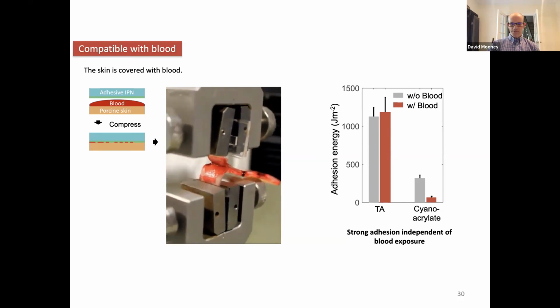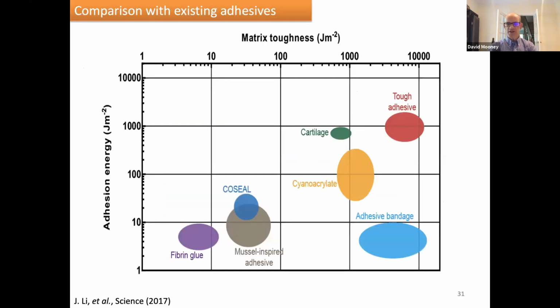still allowing us to use it in these kinds of bloody environments. Now, to put this in context from other materials that are out there, the tough adhesive in terms of both its matrix toughness and its adhesion energy functions in this regime. The cyanoacrylates that many of you are familiar with are over here. The PEG-based materials such as Co-Seal and fibrin-based glues that are used medically today are over in this regime. The mussel-inspired adhesives are down here. So you can appreciate that these tough adhesives provide, at that time, a really unprecedented ability to mediate adhesion and to do it actually in these wet, messy environments in the body.